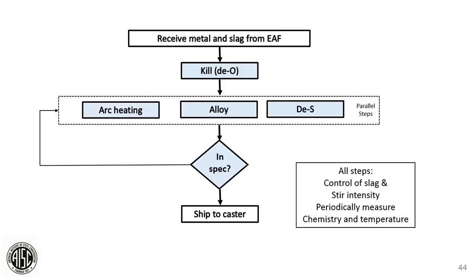So this is where the heart of the metallurgy happens as far as the chemistry additions to the steel. We receive the metal and slag from the EAF. We're going to kill it, and we do multiple things at the same time. We're going to heat it up. We're going to alloy it. We'll get the sulfur out of it, confirm it's in spec. If it's not, do it again, and if it's ready, we ship it to the caster. And in all steps, we control the slag. Stir intensity is controlled, and we periodically measure chemistry and temperature while we're doing that. Next slide, please.